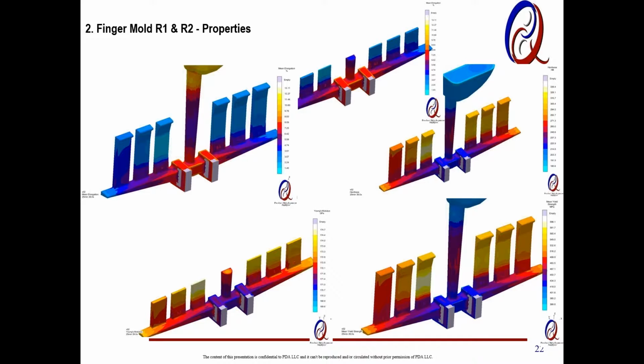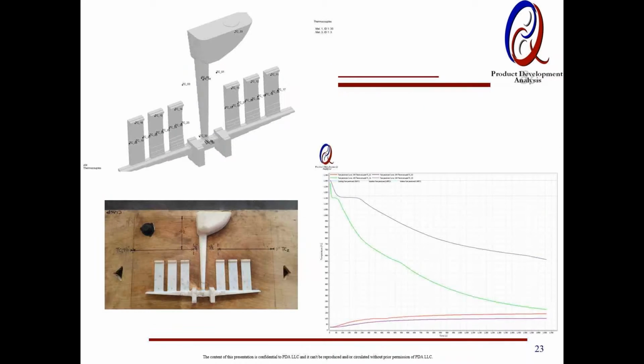And in the thinnest wall, we found around 2% where we really wanted 12%. So that led us to modify the alloy to get 12% elongation in the 2 millimeter wall thickness. And this kind of work helped us create the stage and set up the direction for the research in order to achieve that. So this again also lays out the importance of ICME tool as part of the new product development for thin wall castings.